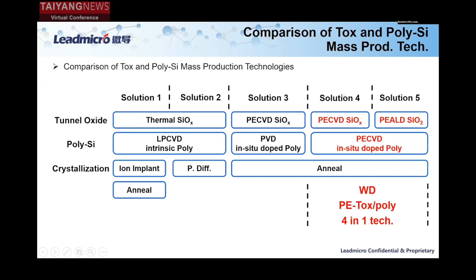Today what we are going to mainly share is solutions 4 and 5, where we use PECVD as the main method to develop the tunnel oxide and in situ doped polysilicon. So for solution 5, both tunnel oxide and polysilicon use the PECVD method. This method is also known as 3-in-1 tech. But for Leadmicro, we also introduce one more option, which is based on the PEALD tunnel oxide. Hence our technology is compatible with PEALD. So ours is the so-called 4-in-1 technology.